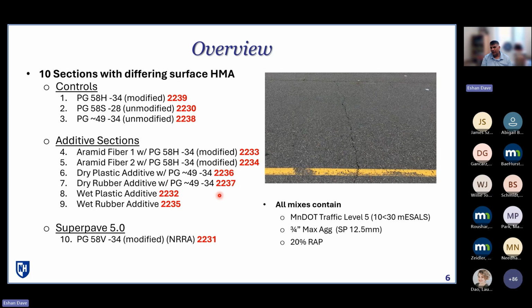Also, if you recall in phase 1 of the NRRA effort, there was one trial with a SuperPave 5 mix, and that had done quite well. So that was considered here as well. So the cell 31 here is essentially a 58V minus 34 modified binder using SuperPave 5 design approach, and that's your 10th cell. Now, keep in mind that these first 9 cells are also directly shared with the additive group experiment, so they are providing data to both studies, and that's why there's this parenthesis NRRA for cell 10, because this one is only unique to the MRCC effort.